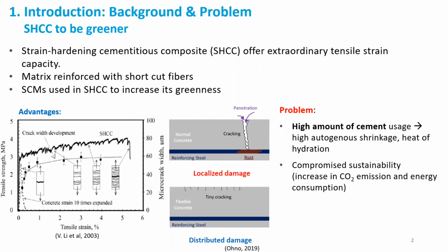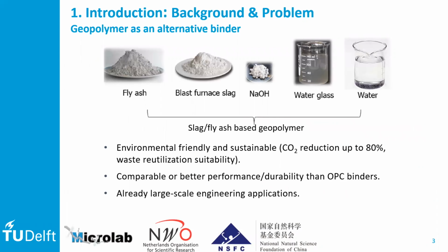However, SHCC has its own problems because its preparation needs a high amount of cement, which could largely compromise its sustainability. Researchers have already applied SCMs into the SHCC to increase its greenness. However, there's still much room left for us to improve. Geopolymer as an alternative binder, on the other hand, is environmentally friendly and sustainable. It also has comparable and even better performance and durability than OPC binders.